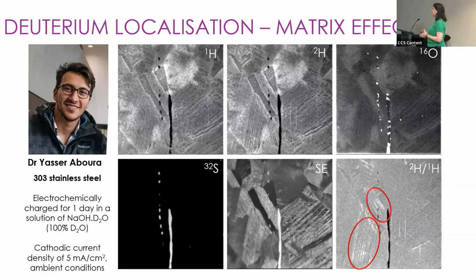And these are actually dislocation slip bands here. So the deuterium has segregated preferentially to these slip bands. And you can see the microstructure is quite complicated here. So that's all I'm going to talk about for the steel. This is still to be published, but it's just a nice example of this first issue that we found we had to overcome.